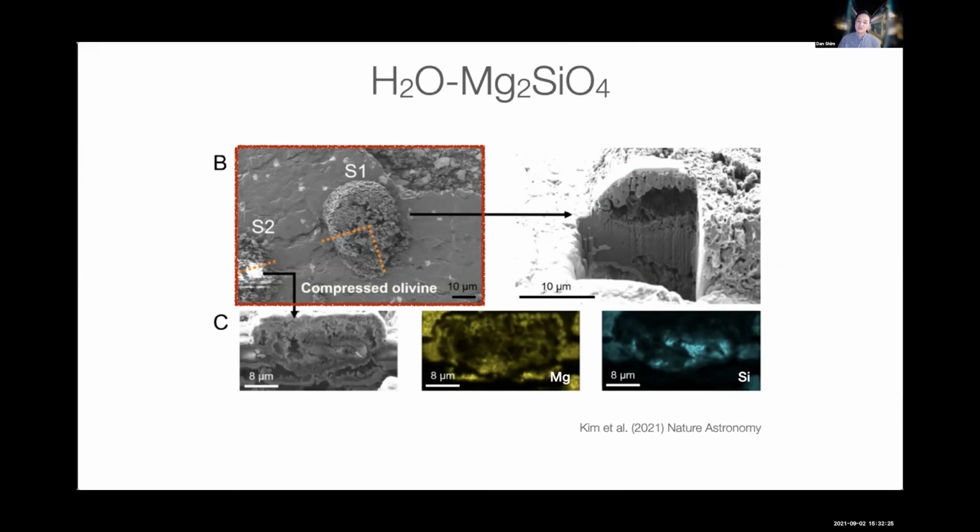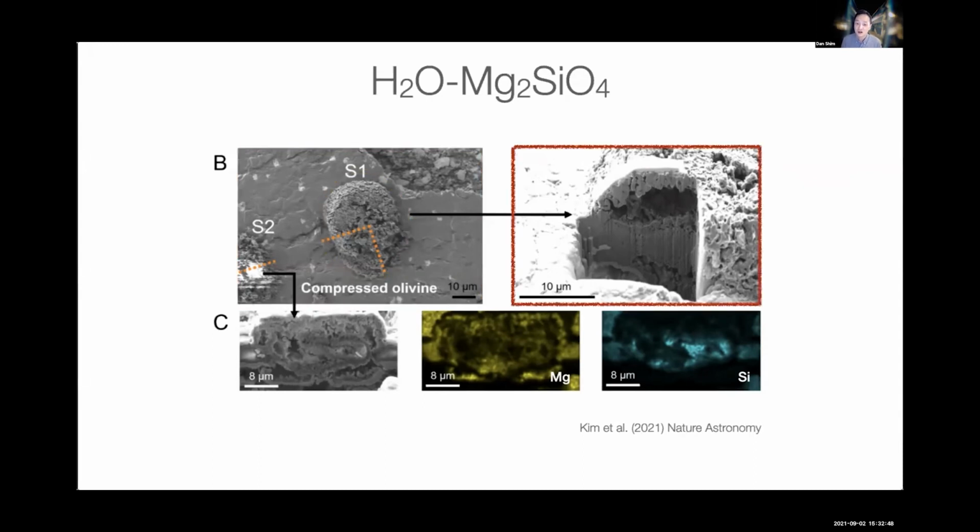What that means, combined with our X-ray measurements, is that magnesium somehow dissolved into the water when it was heated above melting and at high pressure. And by decompressing the sample, the solubility of Mg in water reduced, and then you actually have sedimentation of Mg(OH)2, which is summarized in this reaction.